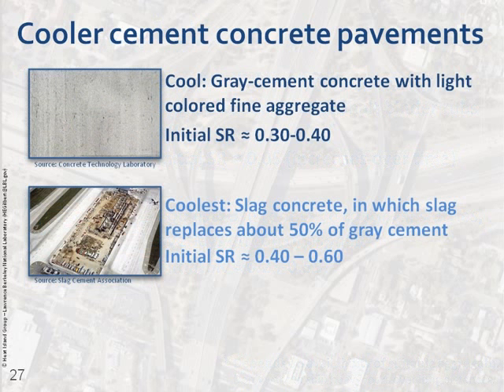When we're looking at cement concrete parking lots and pavements, many freestanding parking structures are constructed from cement concrete, and those are actually pretty reflective in and of themselves. They're within the range that we might suggest, with an initial solar reflectance of 30 to 40%. If you want to achieve an even more reflective surface, or you have other environmental goals, you might think about incorporating slag into your cement mix, which is a byproduct from the blast furnace. And that's actually really light and can increase the range of solar reflectance to 40 to 60%.